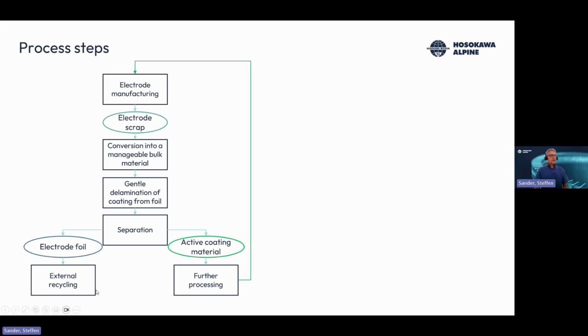This will go to an external recycling, and the active coating material that is collected in the fines of this separation step here, in some cases has to be further processed, and we were thinking that it might be possible to bring this material directly back to the electrode manufacturing, and there's publications out there that indicate that this is really feasible. If you do it right, there's no detrimental effects on the quality of the electrodes. That's the lab scale still, but I think I'll show that we are part of a joint project where we would really like to challenge this process and go to the next scale here.